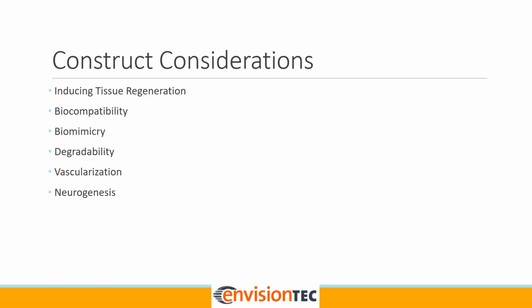Vascularization. This is particularly important in constructs greater than a 1 millimeter cube. As it turns out, if you create a scaffold greater than that size, without any blood vessels, the tissue will become necrotic and die. So even if you manage to make it as far as inducing the correct kinds of tissue, without that vascularization, that tissue will die. So we need to incorporate certain, say, growth factors or geometries that are conducive to creating those blood vessel networks that will then integrate into the body.